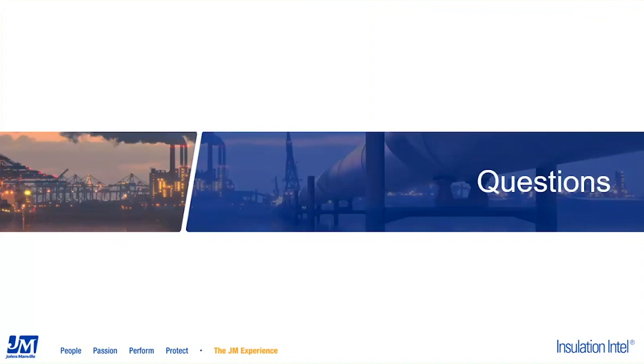Is it possible to find CUI in stainless steel pipes on cryogenic services? It's possible, but very unlikely, unless the pipe is undergoing a cyclic temperature system. The stress corrosion cracking of austenitic stainless steel is a temperature-related phenomenon. It only occurs between approximately 140 degrees F and approximately 250 degrees F. We can argue a little bit around those numbers, but certainly nothing much below 100 degrees F. So if it was a cryogenic pipe, the chemical reaction of stress corrosion cracking would simply not occur.